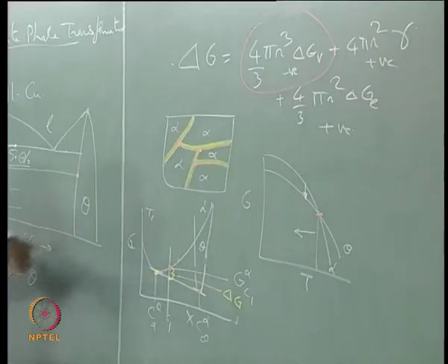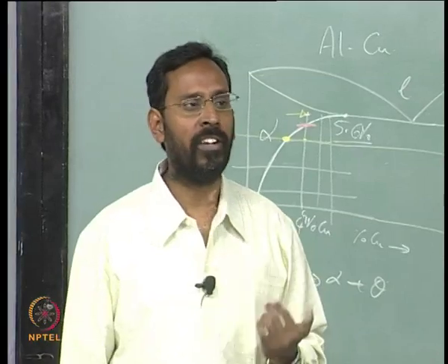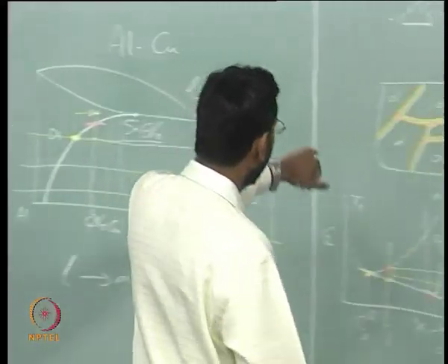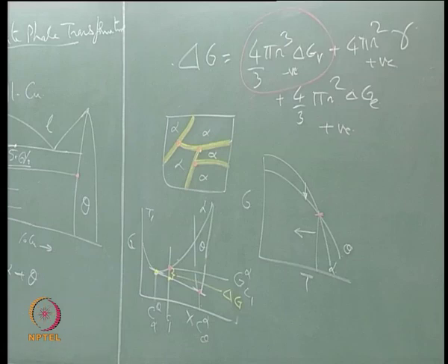That is the reason why the system chooses the triple junctions and the grain boundaries for nucleation. First and foremost, the triple junctions are regions in a high energy state. As a result, the system can easily relax to a low energy state if nucleation occurs there.